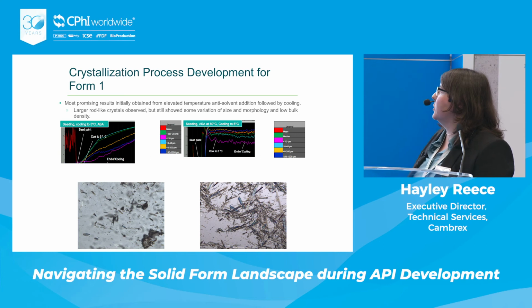So from this data, we get an idea of how controlled the process is, and it wasn't controlled at all. And you can really see it from the particles on the bottom there, that we're getting different size crystals, and a very elongated rod-like particle was obtained from this crystallization. So definitely not ideal and not controlled at all.